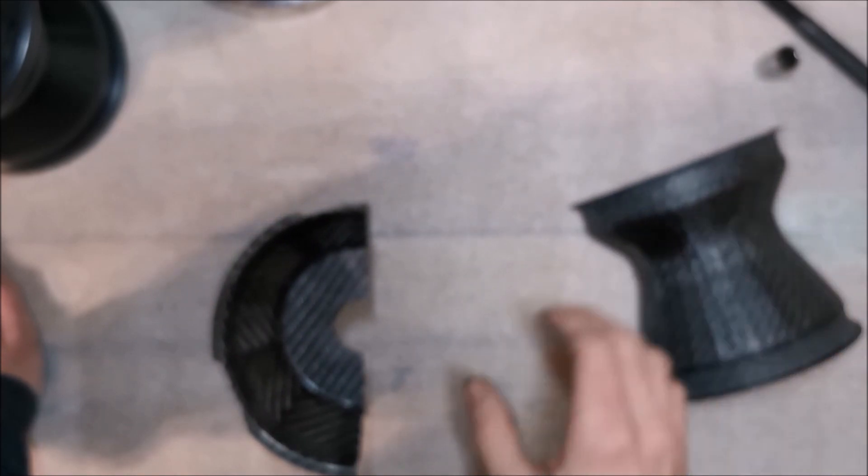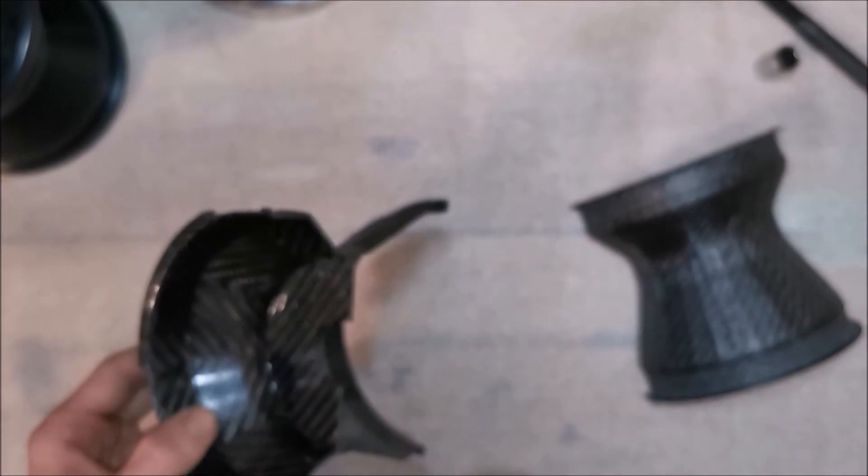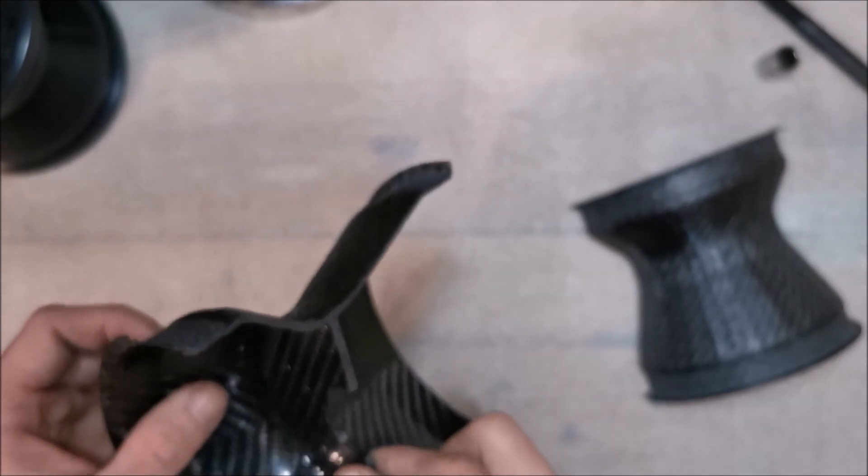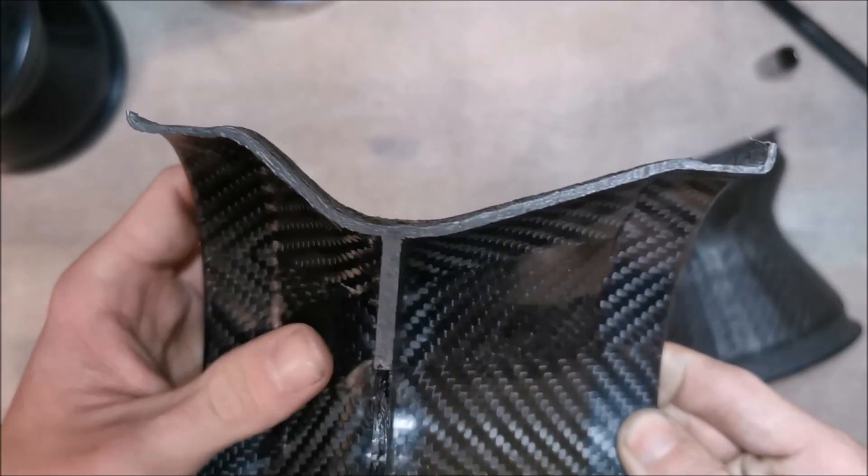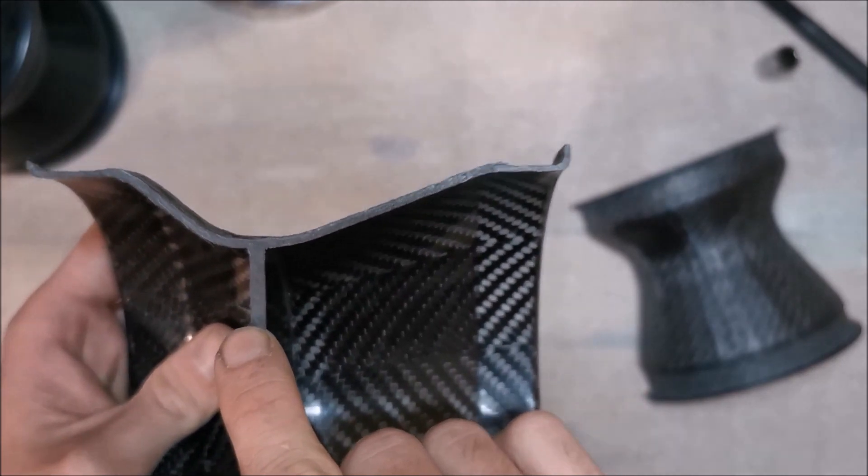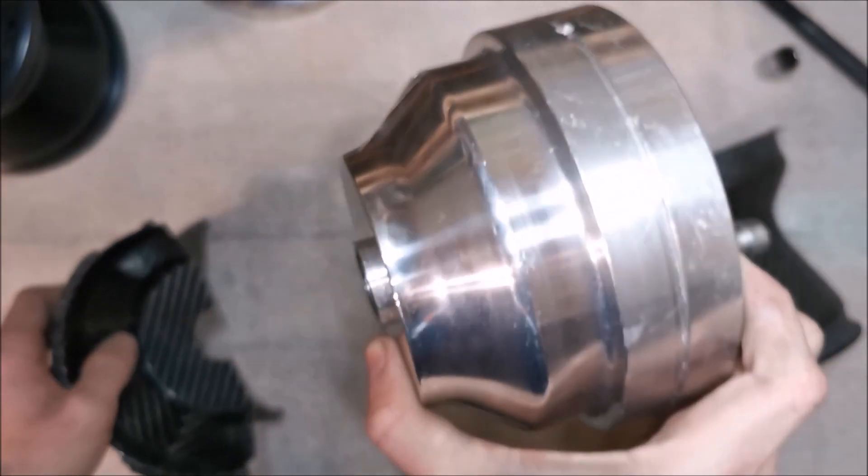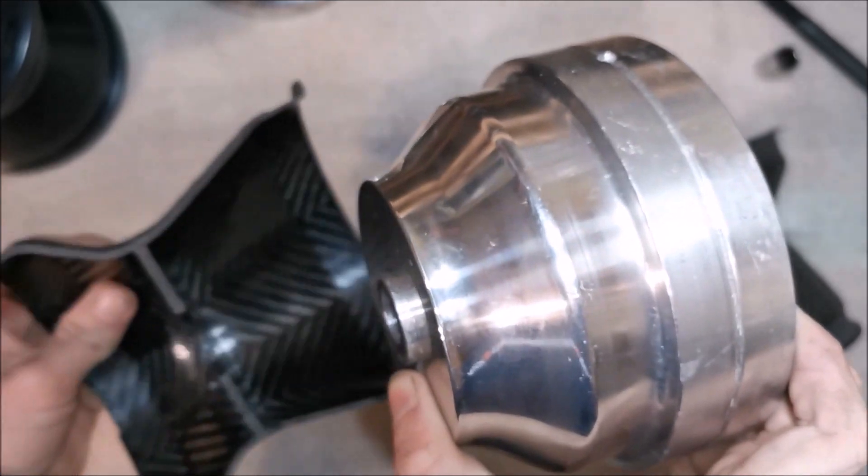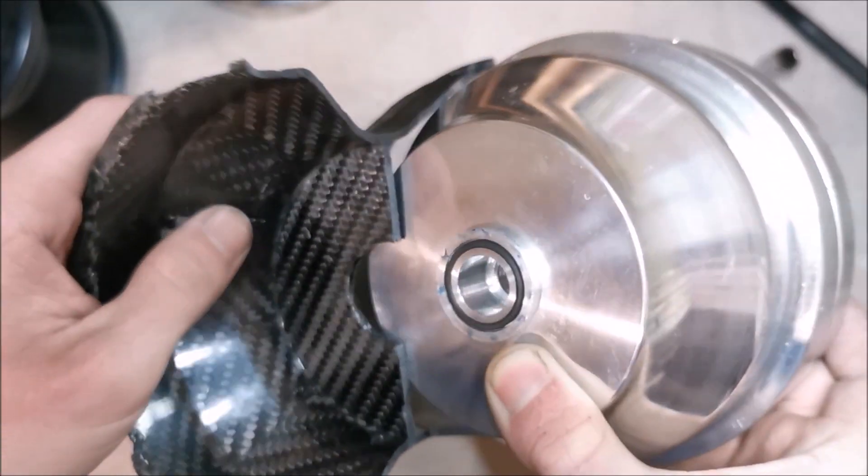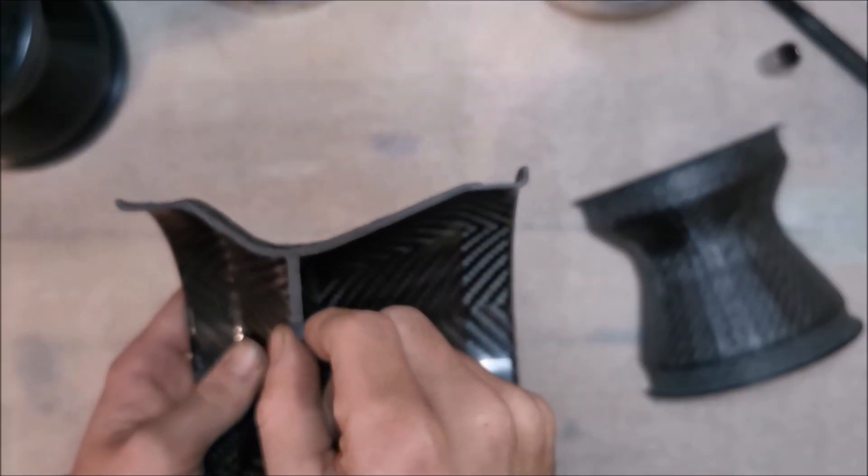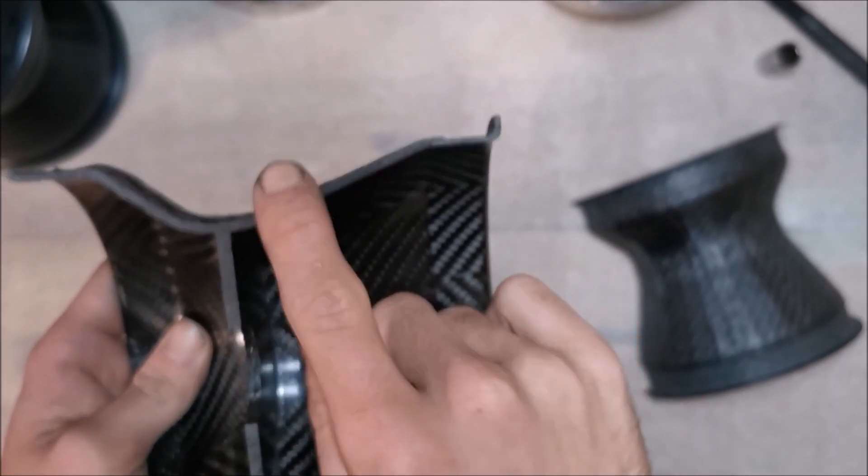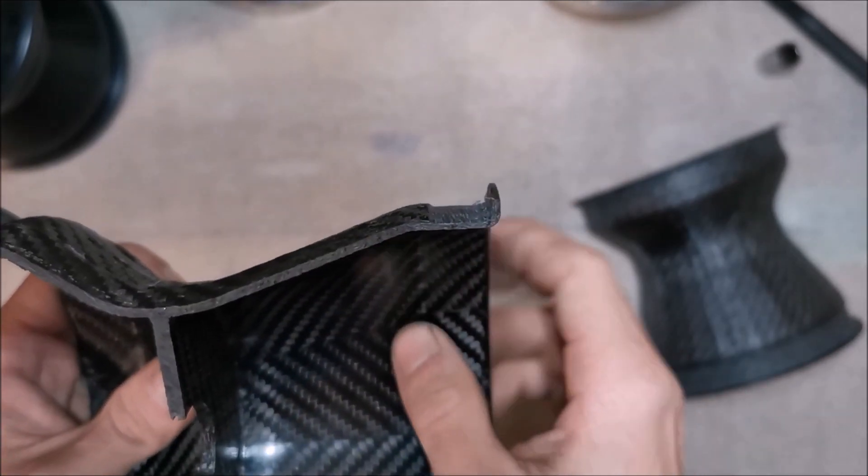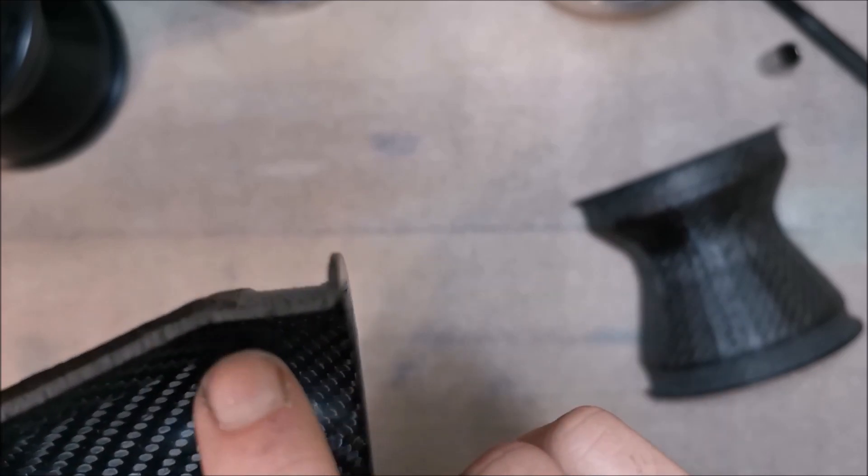The next part is probably the part I can also use on a go-kart when everything goes right. But this part looks much better. If you see here the wall thickness. This is the thickness on the mold which is created here with this. As you can see it lays like this. This is 3.5mm. And then this is also pretty good. This is around 2.5mm thickness.